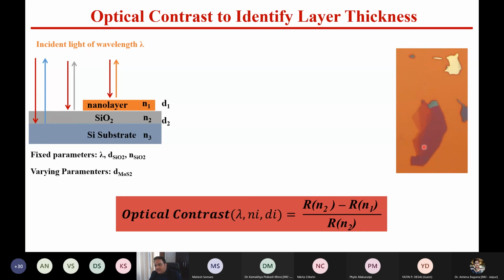You have an exfoliated flake. You see this is a very thick flake. Now you can see here, this is the blue color, so it goes from yellow to blue to purple to transparent. This is what the monolayer is. This is bilayer and then trilayer and then the higher order of the layers.